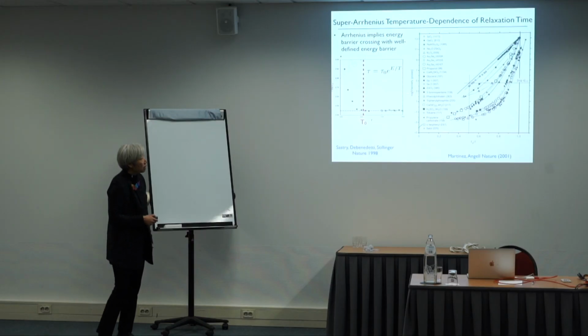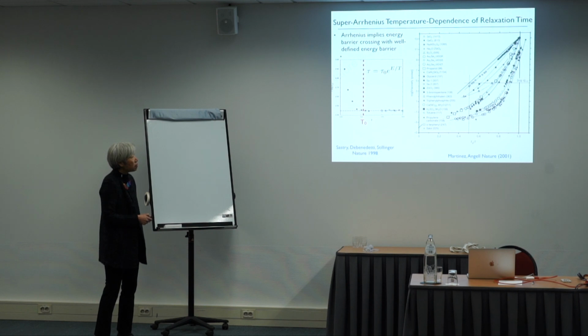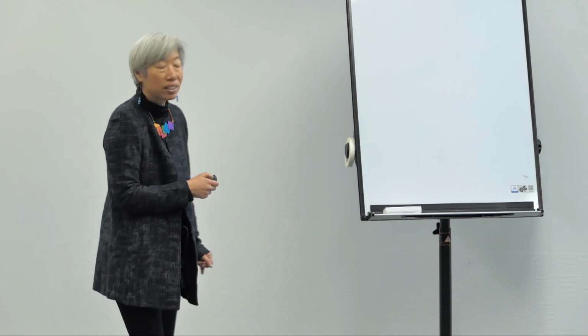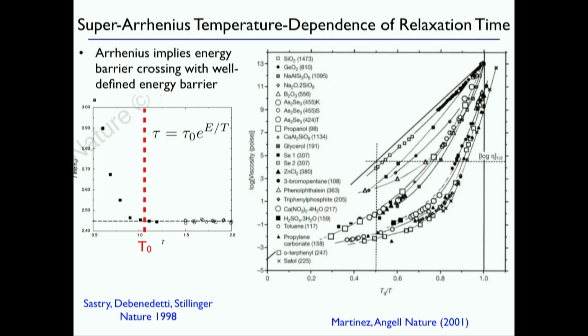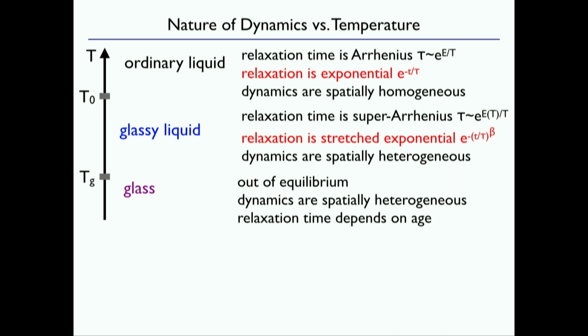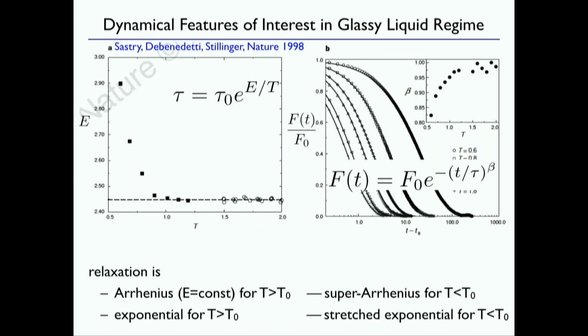And this is showing what happens at the onset temperature. This is a simulation. So at high temperatures, if you look at the relaxation time and extract this energy barrier, it's just flat. So there's a well-defined energy barrier. But below the onset temperature, that energy barrier just gets bigger and bigger. So the relaxation time is slowing down faster than you would expect. All right. This relaxation being exponential. So here is the relaxation function.